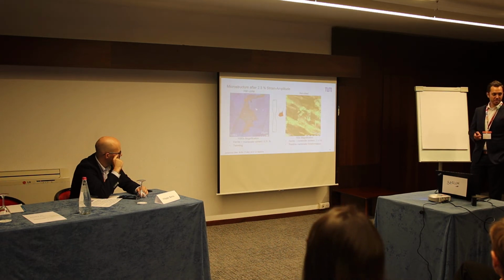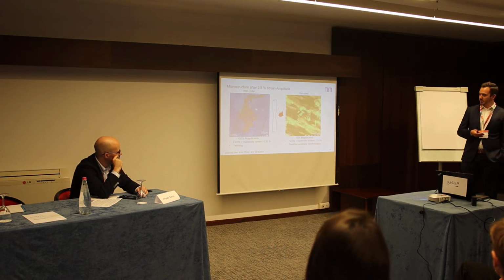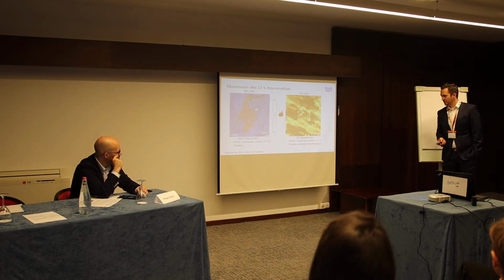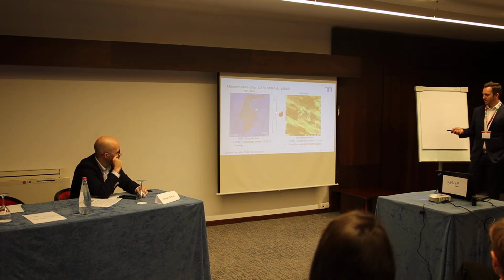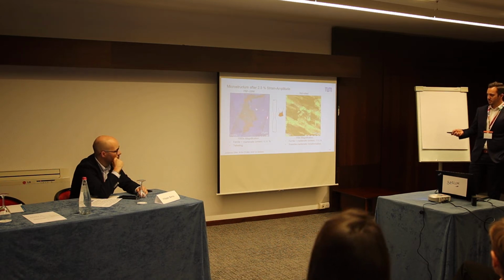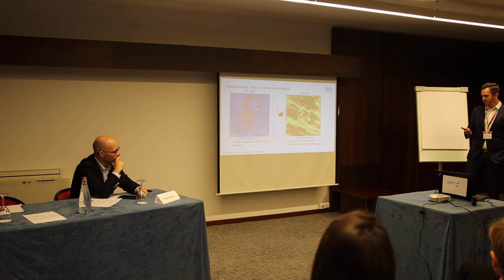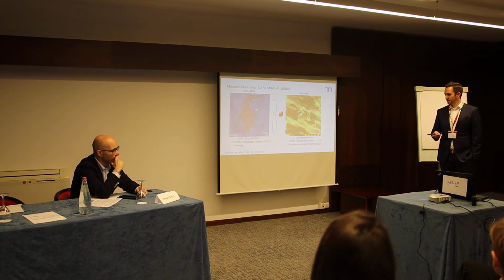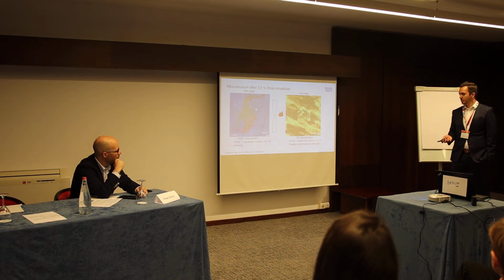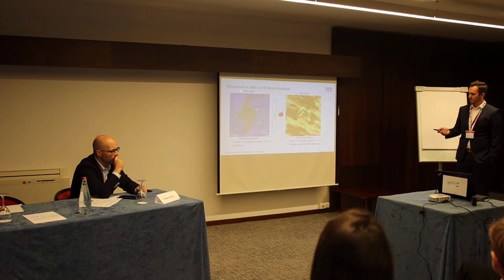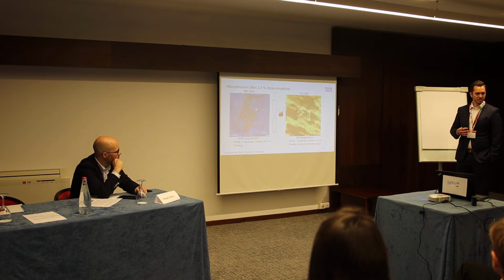So let's take a look at the microstructure after 2.5% strain amplitude, because I think these are the most interesting ones. There we did a longitudinal cut from the fracture surface, the bottom or the top, which you can see here in the middle. We embedded it in resin, polished it, and etched it in the end with Beraha etchant, so we can see the different grains. Here we can see small slip lines inside a large grain of the PBF-LBM manufactured 316L. However, the subgrains, as I would call them, weren't really affected, but I will get to that later on.